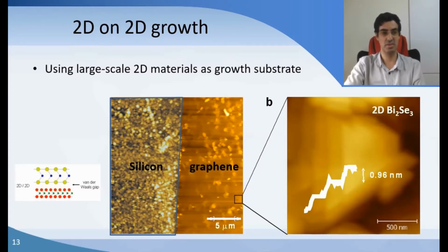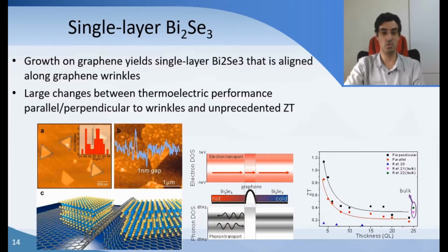Because of this van der Waals interaction, that growth substrate is interacting much less than you would see for, let's say, silicon. In this case, we see that silicon grows clusters, whereas graphene would grow thin films, in this case of bismuth selenide. Interestingly, these films are not epitaxially ordered to the graphene surface. Instead, they are aligned with wrinkles that are forming on the graphene. So that tells you that the van der Waals interaction is weak enough that the grain can orient itself on the wrinkle and then grow out from there.